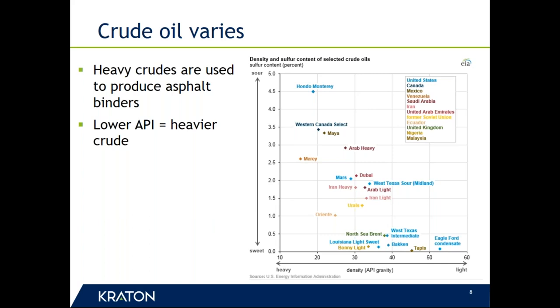The heavier the crude is, the more likely someone's going to be able to produce asphalt binder from it. In fact, you have to have a heavy crude in order to make some asphalt. The lower the API, or the gravity, as it's called, of the oil, the heavier the crude is. And so the ones on the far left, which you would typically see used maybe as the stock for one of the blend sources for making asphalt binders at a refinery, those on the right are less valuable for that.